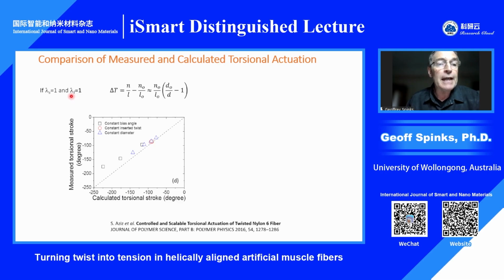So we could assume that our lambda L was unity from observation. We made a second assumption that the string length or the helical path length also would not change. That was based on the idea that the helical path in all of these systems is made up of very stiff filaments, either bundles of carbon nanotubes, which are very stiff in tension, or oriented polymer crystals, like in the twisted nylon fibers, also very stiff in tension. So we made an assumption that the helical path length is constant.